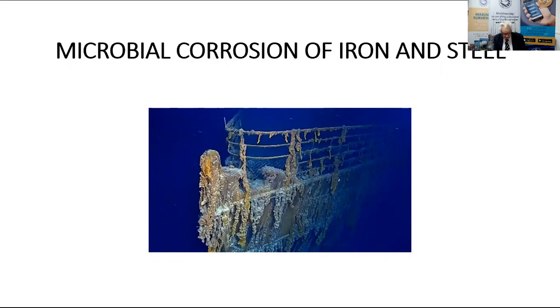The impact can be enormous, and it's estimated that 20% of all corrosion damage is caused by microorganisms, leading to costs as high as 2.5% of a country's gross domestic product. That's a lot of money. There's also been a very large amount of data published on this subject in the civil engineering field over the last 20 years or so, and it's widely recognised that not only does MIC stimulate general pitting, crevice and stress corrosion, but that it is also capable of enhancing other related defects in steel, such as corrosion fatigue, hydrogen and nitrogen embrittlement, and cracking.